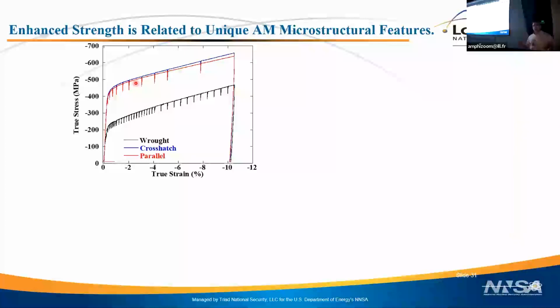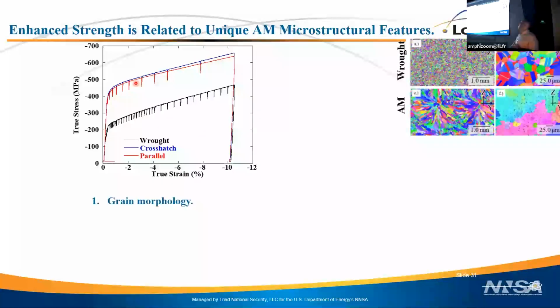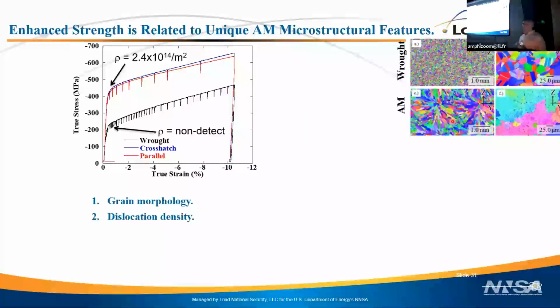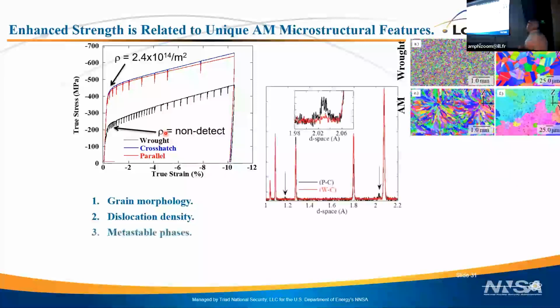Of course, you expect it's the microstructure, but there are lots of features in the microstructure that are different. First of all, the grain morphology. If you compare wrought material up here to AM material, you see the grains are very different. And of course, the grain boundaries dictate how dislocations can flow, so that can affect the strength. Another difference is dislocation density. We measure the dislocation density in the AM material, it's actually quite high. You get a lot of plasticity during additive manufacture. In the wrought material, it was non-detect, so it was below our instrument resolution. So that affects the strength of the material.